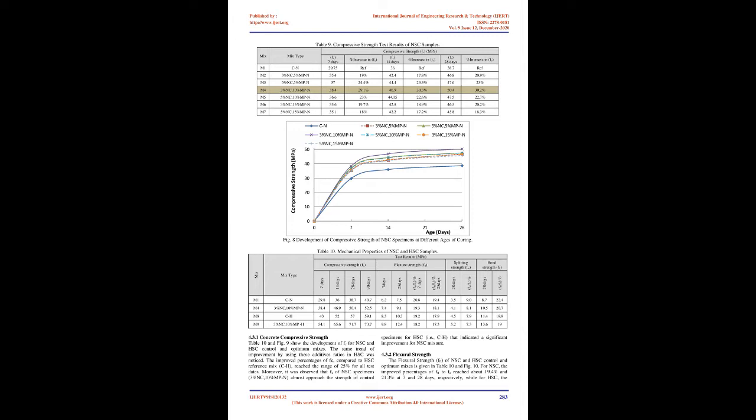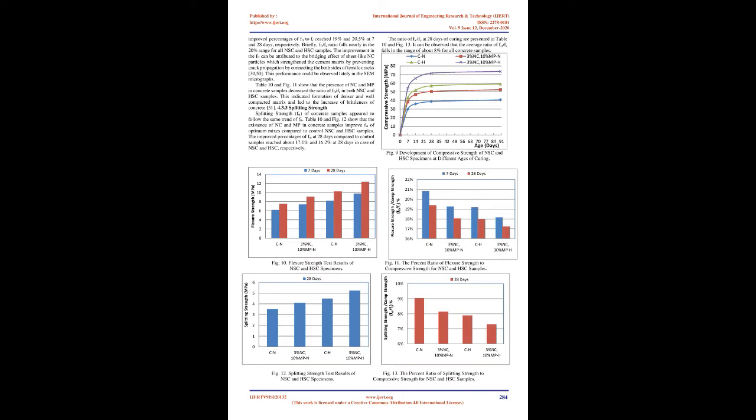For mortar mixes with 5% NC partial replacement of cement, the enhancement in FC compared to the reference mix at 7 days reached 15.86%, 13.03% and 29.63% for sonicating, stirring, and sprinkling after stirring techniques, respectively. While these ratios increased to 18.29%, 15.02%, and 31.31% at 28 days, respectively.